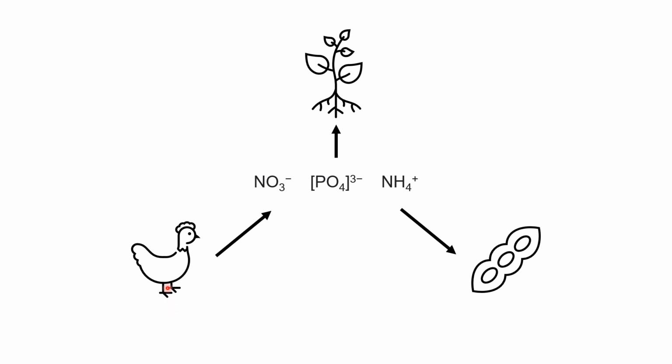Looking back at this diagram, the initial idea was that poultry litter biochars would release the nutrients, and those that weren't used by plants would then be adsorbed by lignocellulosic biochars. However, we've seen that although poultry litter biochars are biased towards leaching and lignocellulosic biochars are biased towards adsorption, both biochars perform both functions. And in fact, in the case of ammonium, poultry litter biochars purely adsorb, and therefore it would be necessary to add ammonium in the form of conventional fertilizer to soils in addition to this biochar regulation system.